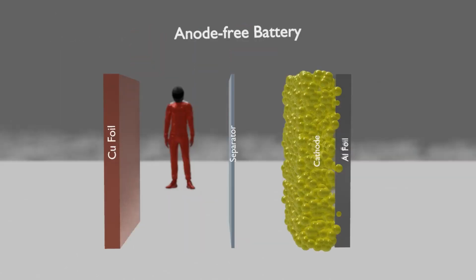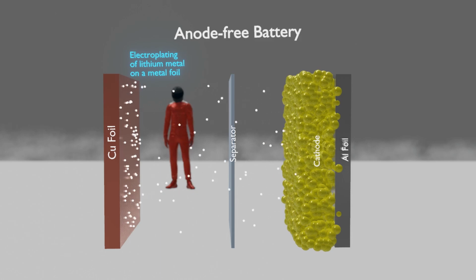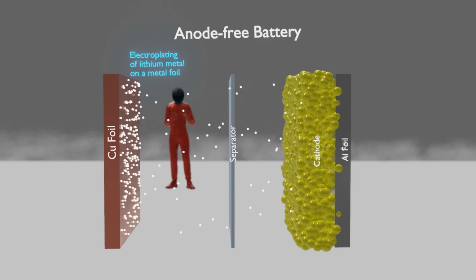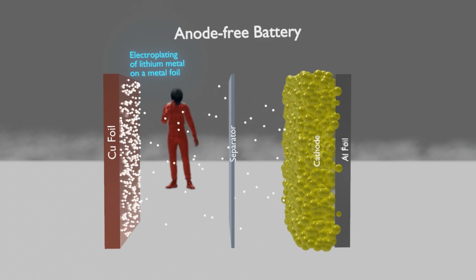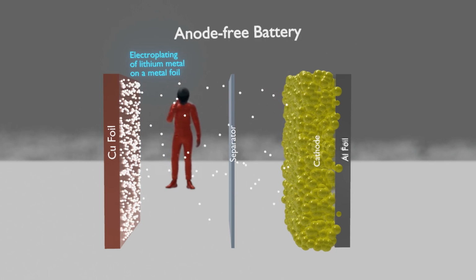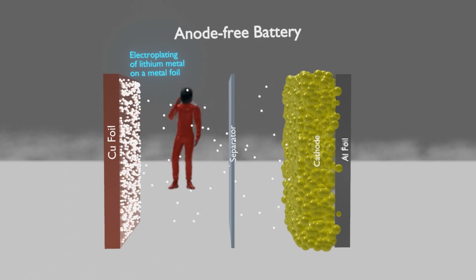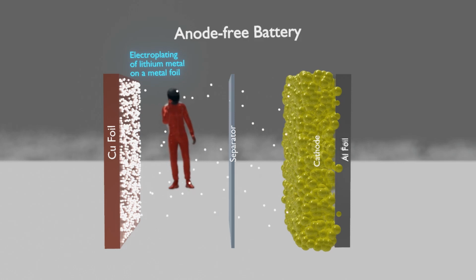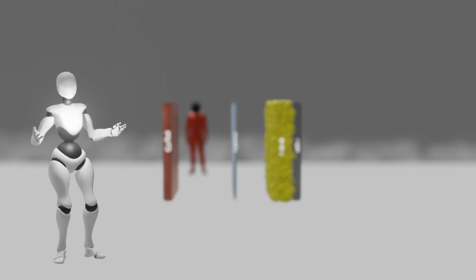The absence of anode material does not mean that the battery will not work. When the battery is charged, the lithium ions present in the cathode material begin to move in the negative direction and form a lithium film on the metal foil that acts as a current collector. It proceeds in a very similar way to electroplating. However, while conceptually brilliant, manufacturing a real battery in this way introduces a variety of problems.